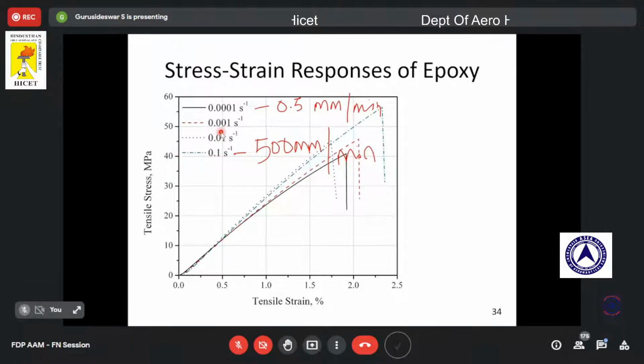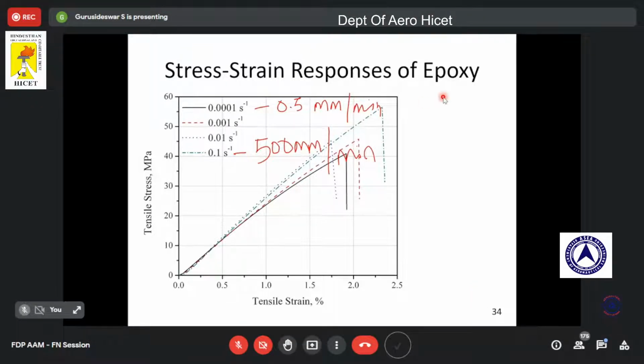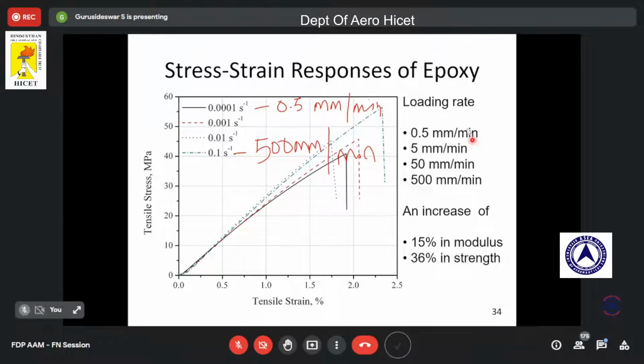Now, when I do the testing at a higher strain rate, at a higher loading rate, you can see there is an increase in the strength. And also, one can see there is a drastic increase in the slope. The slope will give my Young's modulus. So from this figure, one can understand the polymer is rate sensitive. So we have taken 4 different strain rates, loading rates. When we do this tensile testing at these strain rates, we could find the change in properties.